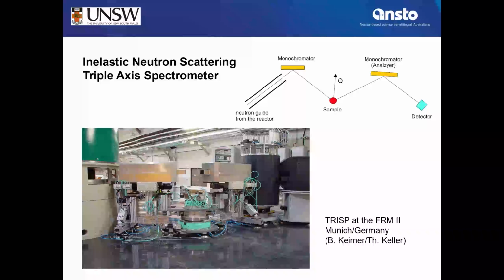So we need a trick here to distinguish, and the trick, that's not shown in that cartoon, sorry for that, is that we can place a spin flipper into that field. A spin flipper is a high frequency electromagnetic field, and if tuned directly, you get a resonance with the neutron spin, which flips the spin up again.